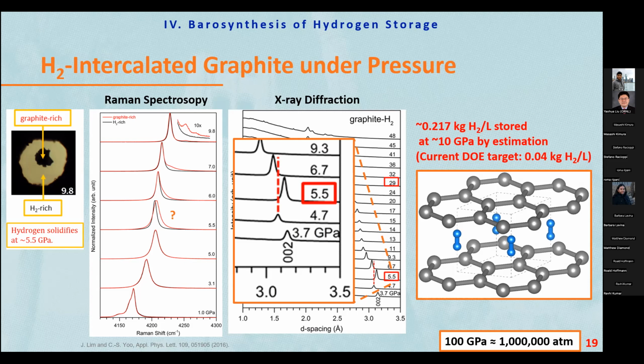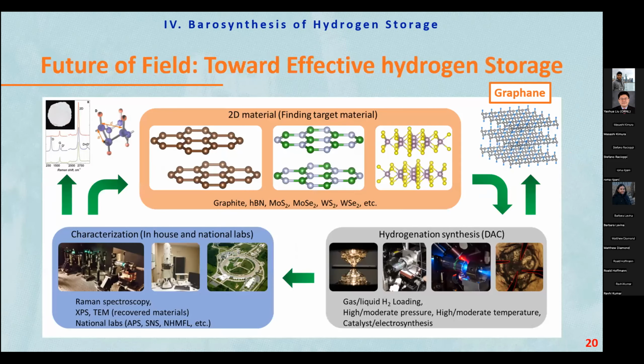And we can further develop this graphite hydrogen storage idea for high pressure study. One could make graphene formation as a bulk, using high temperature or laser heating and so on. And once the hydrogen is stored in the graphene layer, I think there's more chance to have this graphane formation, graphene with hydrogen attached. So that could be future research as well. And I think this high pressure equipment, the diamond anvil cell, can explore these effective hydrogen storage materials.